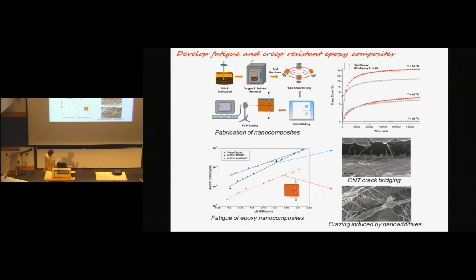This plot over here on the right-hand side shows you creep strain of an epoxy graphene composite versus time. The red curve shows neat epoxy, and the white curve shows the behavior of the composite, graphene epoxy. And you see what happens at room temperature. There is not much difference between them, but as the temperature goes up, then the filled epoxy, this curve, actually does better, in the sense that the creep strain is smaller. So this material creeps less. It is interesting that it creeps less at higher stresses and at higher temperatures, that is, under conditions which are more demanding than room temperature.